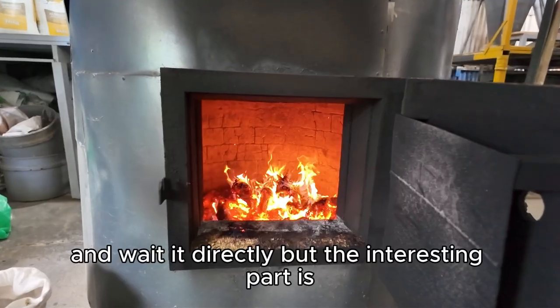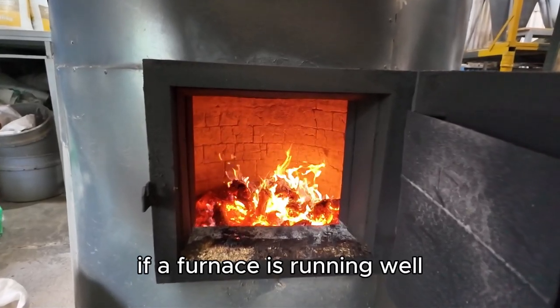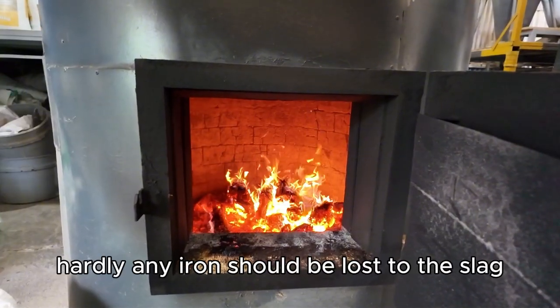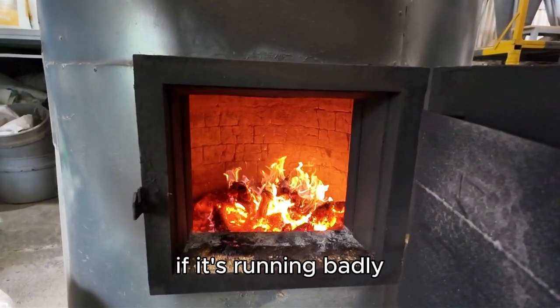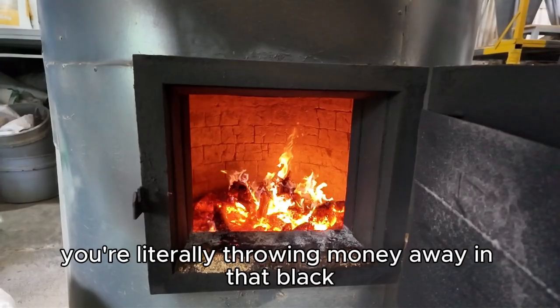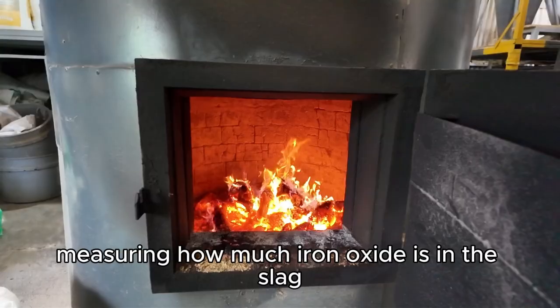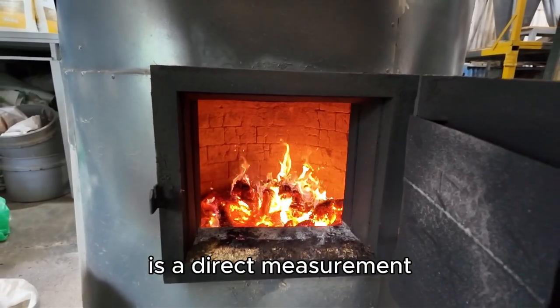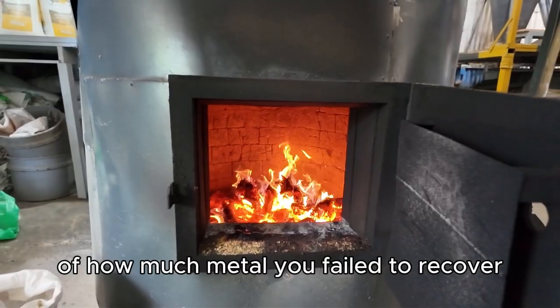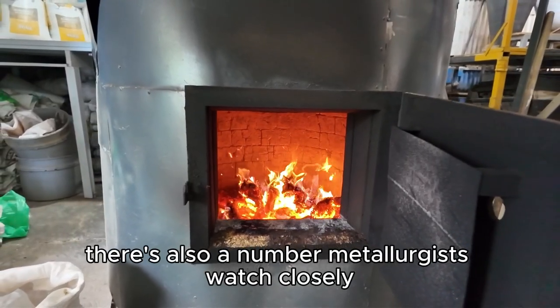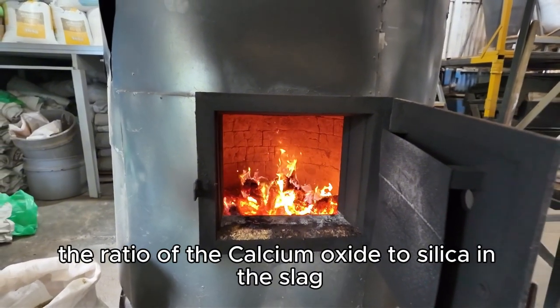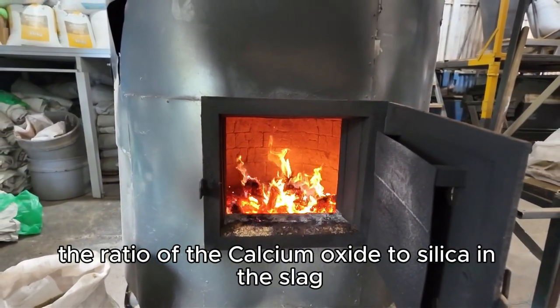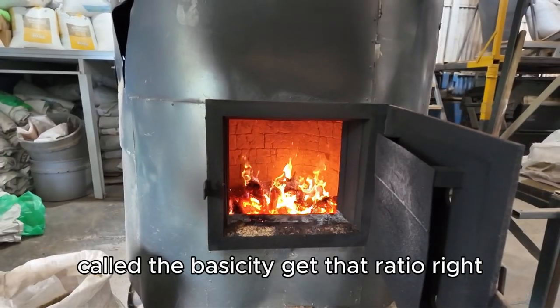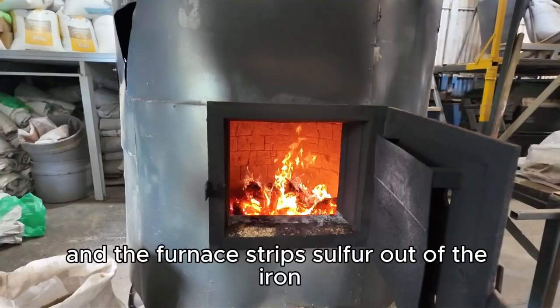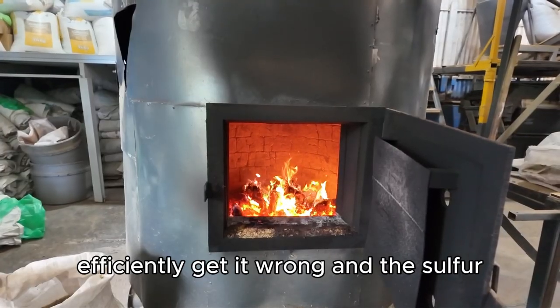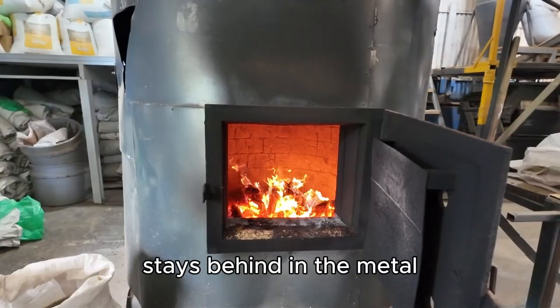But the interesting part is the iron that's still trapped in there. If a furnace is running well, hardly any iron should be lost to the slag. If it's running badly, you're literally throwing money away in that black glassy rock. So measuring how much iron oxide is in the slag is a direct measurement of how much metal you failed to recover. There's also a number metallurgists watch closely: the ratio of calcium oxide to silica in the slag, called the basicity. Get that ratio right, and the furnace strips sulfur out of the iron efficiently. Get it wrong, and the sulfur, one of steel's worst enemies, stays behind in the metal.